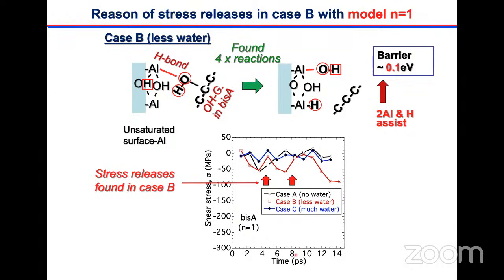This is the reason, what is happening in case B. In the case of n equals 1, there is a hydroxide group here, and this oxygen has a small amount of hydrogen bonding with the unsaturated surface aluminum, because this is an amorphous surface oxide. Then this oxygen goes to here, this hydrogen terminates the oxygen, and then this hydrogen goes to the other aluminum. So this kind of exchange reaction occurs in case B. The barrier energy is only 0.1 electron volt. This small barrier is because the 2 aluminum atoms and the hydrogen on the amorphous surface oxide assist this kind of reaction.